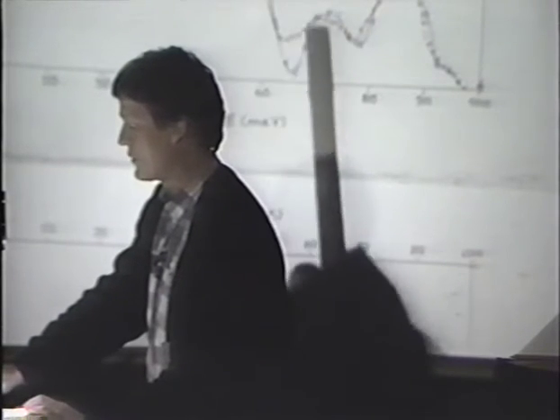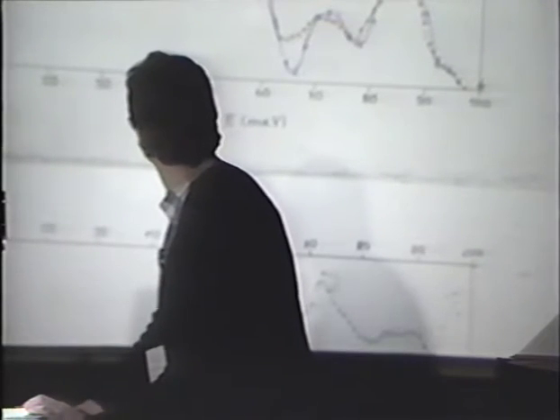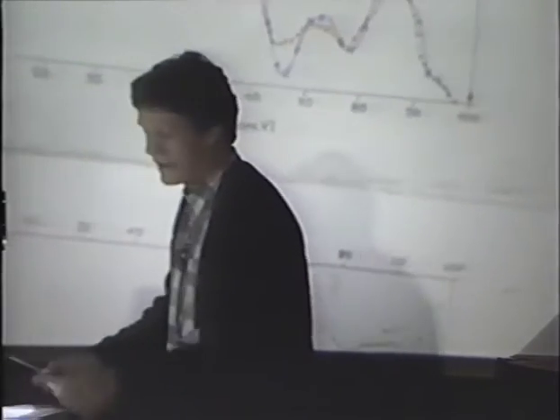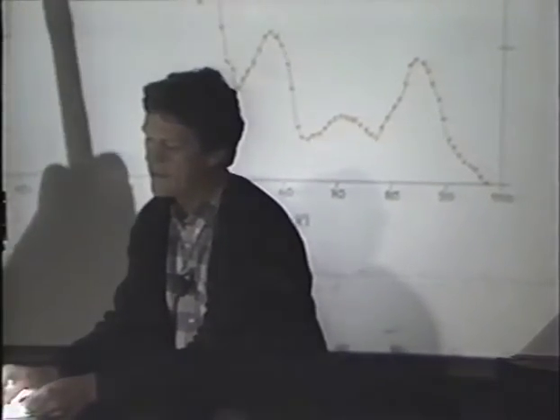The gap here, that's a resolution effect. The resolution is very bad here so far out. So you see it is very much the same. There's no temperature effect to be registered. The middle band of the spectrum, I don't want to display out of time reasons. There is also the middle part of the spectrum from here to here, we measured this with 80 millielectronvolt incoming energy, and it is also very temperature independent.